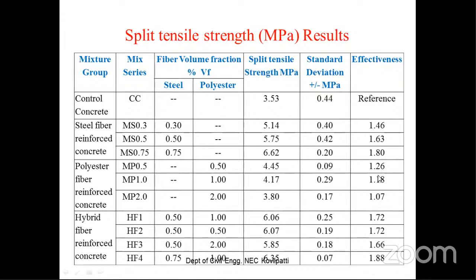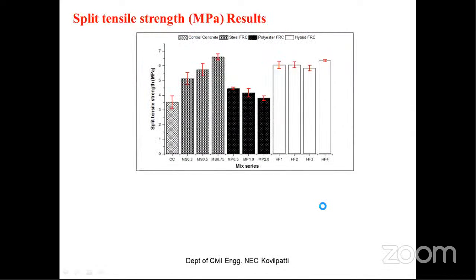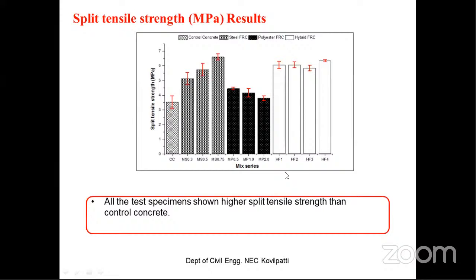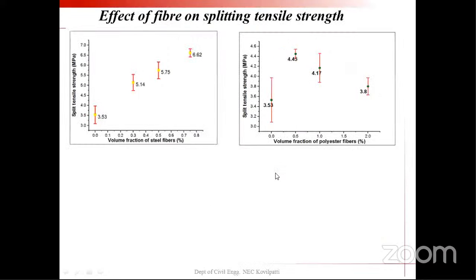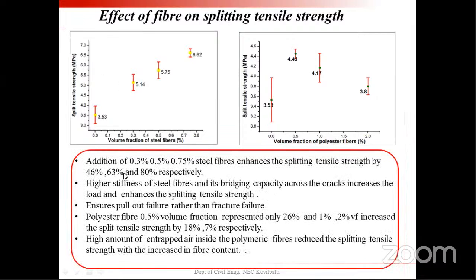But in polyester fiber, it is ranging from 18 to 26. Again, in hybrid fiber reinforced concrete, it is ranging from 66 to 88. So you can see a very good improvement in split tensile strength. All the specimens have shown higher split tensile strength than the control concrete. And again, the analysis was made with the help of values obtained in the single fiber concrete, volume fraction versus split tensile strength. So you can see the enhancement for steel fiber is ranging from 46% to 80%.